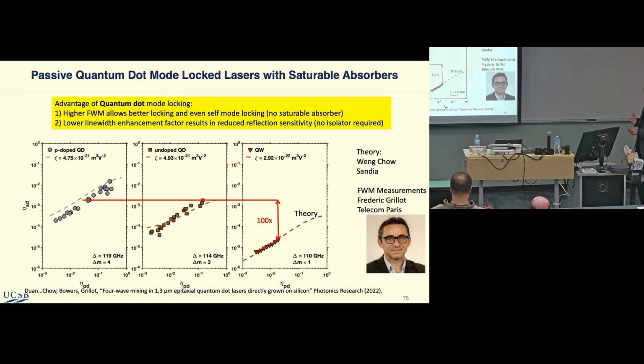So we're making quantum dot devices, and people talk about magic mode locking with quantum dots - they don't even need a saturable absorber, they just mode lock by themselves. The reason is that the four-wave mixing coefficient is 100 times higher in a quantum dot. That's theoretically predicted - Weng Chow did all the theory for this, and our measurements agree with his predictions.